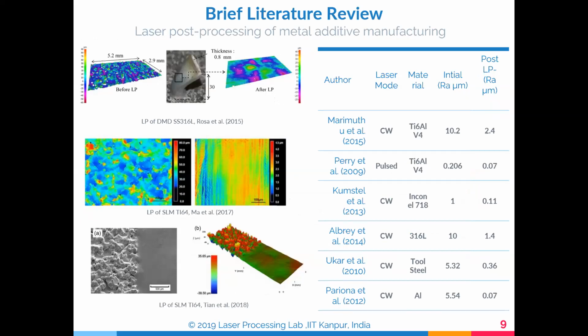Now when we look at some of the literature available for post processing of metal additive manufacturing, they have used continuous laser and pulsed laser. These are all the workpiece materials which have been tried. Initial roughness is 10.2 and final roughness is 2.4. So much reduction happens. You can't always go from 10 to 1 micron; you have to do it step by step. Maybe 10 to 2.4, then from 2.4 you do post processing and might go up to 1. Then 1 goes to 0.1, 10 goes to 1.4, 5.2 goes to 0.3, 5.4 goes to 0.06.